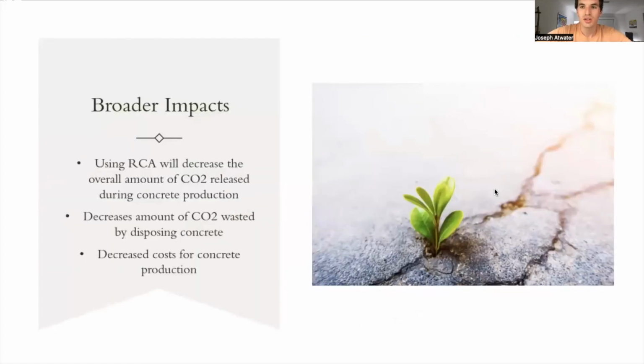Because RCA does not need to be transported over long distances from typical mines, less CO2 is released during the transportation of RCA to a concrete production facility and finally to the construction site. The CO2 emitted for a typical cubic yard of concrete is around 400 pounds, and by reusing concrete instead of disposing of it, this CO2 is not generated completely for waste, decreasing the overall carbon footprint of the construction industry.